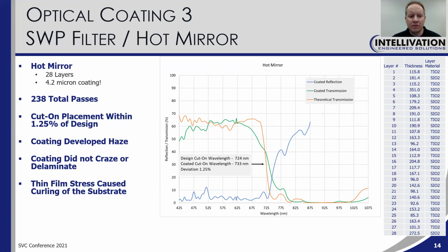The coating did have some haze, but it didn't craze or delaminate. And thin film stress did also cause some curling of the substrate. Things like this can be mitigated with further process development. The curve here shows the performance of the coating compared to the design, and you can see the agreement is pretty good.